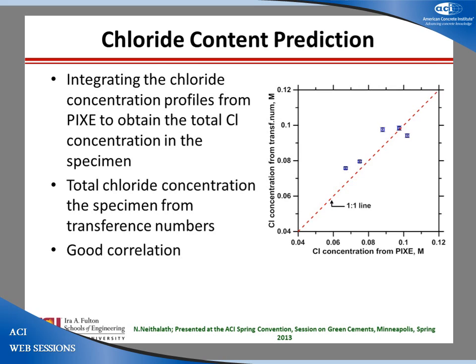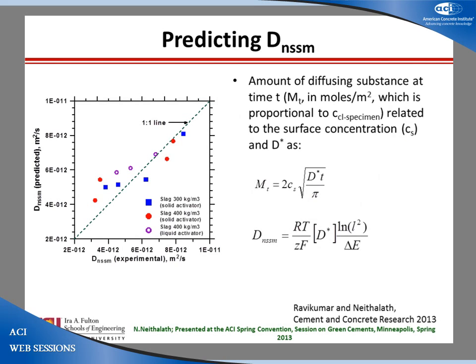And the comparisons between chloride concentrations from transference numbers and a few mixes that we did using PIXE show a very nice correlation and very consistent results too. And if you want to predict the non-steady state migration coefficient, you can play around with Fick's law a little. Crank's book on diffusion gives the solutions for all of these. There are a lot of software packages. For example, MATLAB now has a new inbuilt Fick's solver. Fairly nice. So you can actually look at the total mass of chlorides that went through, and then you can find the non-steady state migration coefficient.